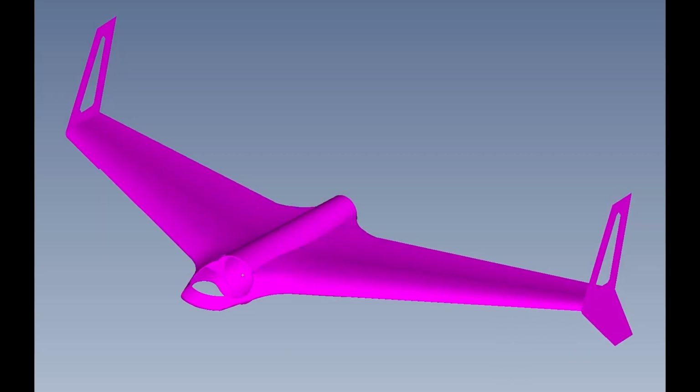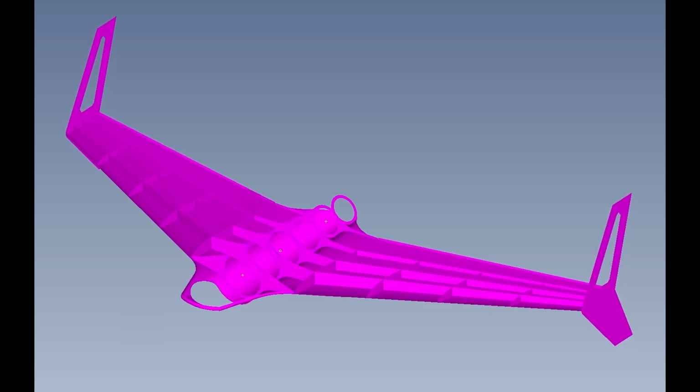As shown in the analysis, all three criteria delivered comparable results, with the highest failure indices occurring near the corners of the fuselage rings. And as predicted, the Tsai-Hill criterion yielded the most conservative predictions.